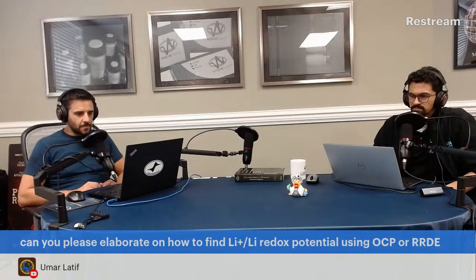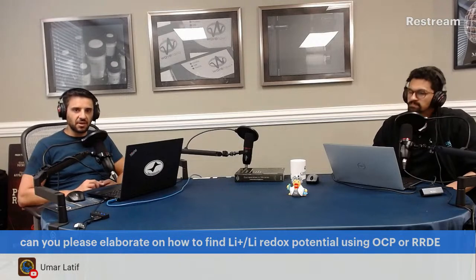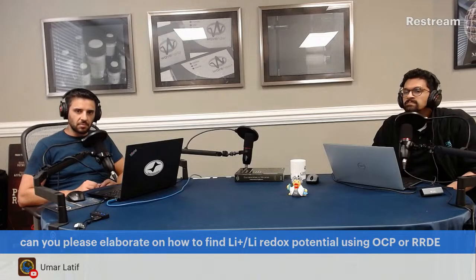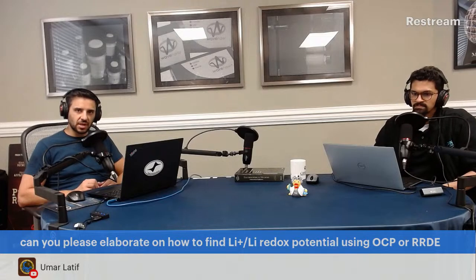And so you simply do cyclic voltammetry very, very slowly. I'm talking like 100 microvolts per second, so 0.1 millivolt per second scan rates, really, really slow, over a wide potential window, and you look for where the peaks are. It's very similar to CV of anything. It's just that you're always going to scan very slowly, because otherwise it's equivalent to very rapid charge discharge, and it's a bad idea to do that to a battery, basically. And so you'll find the redox peaks.